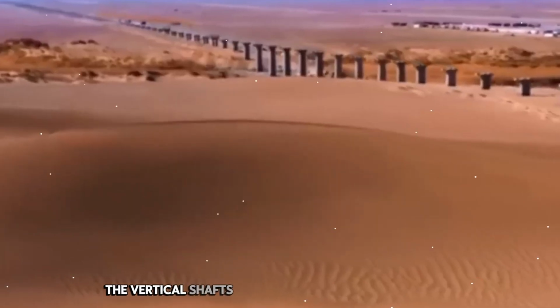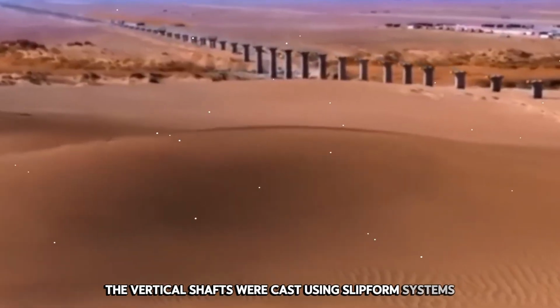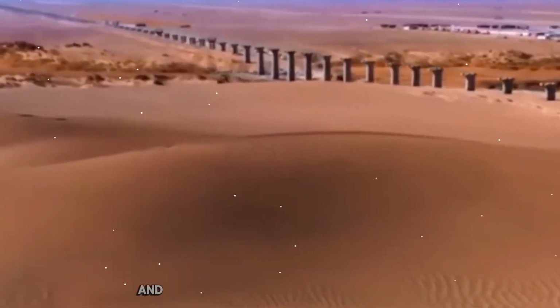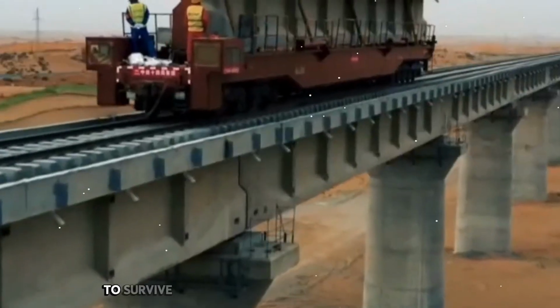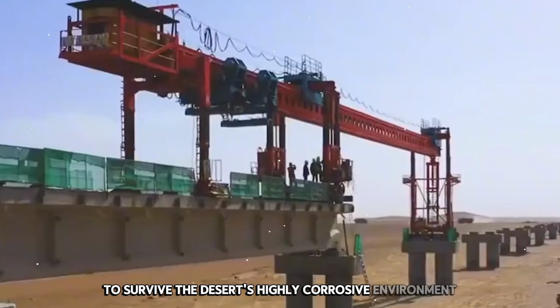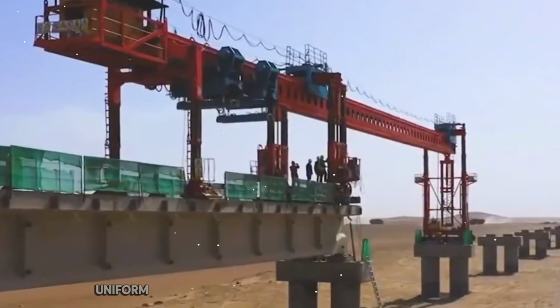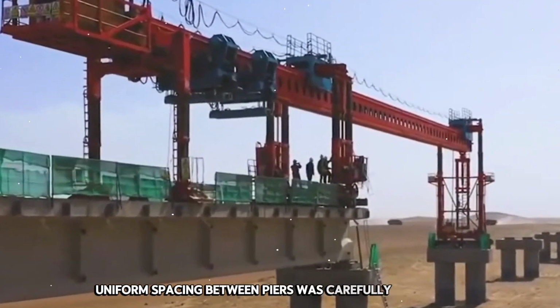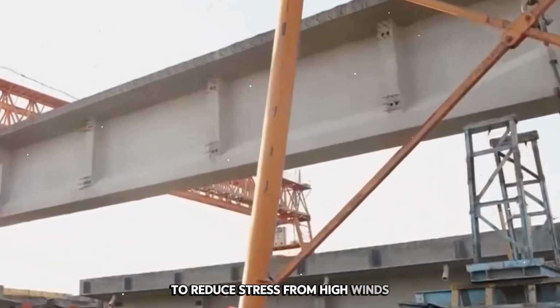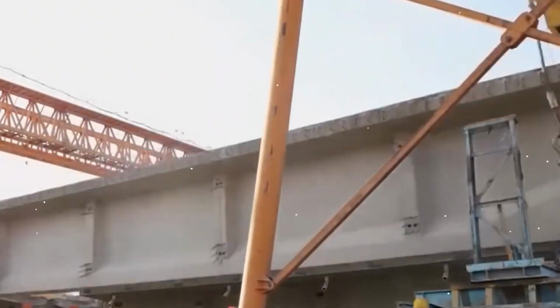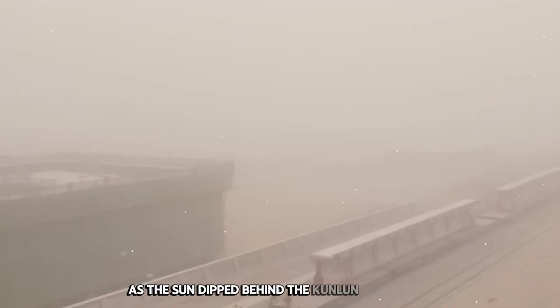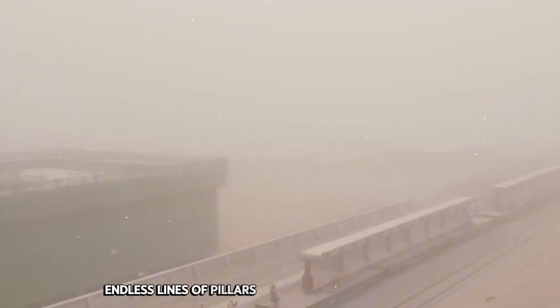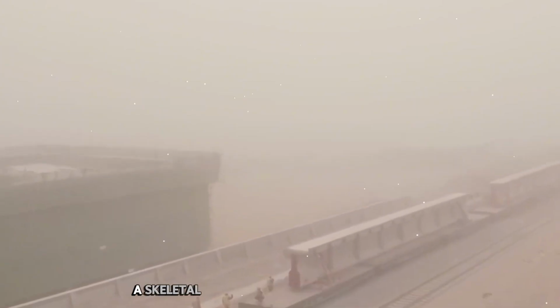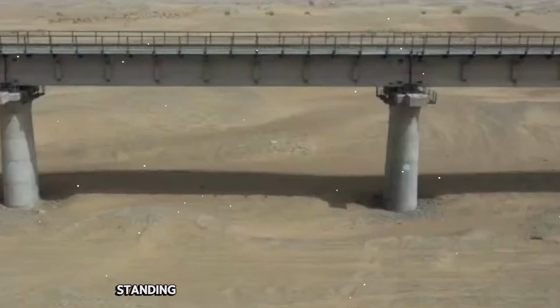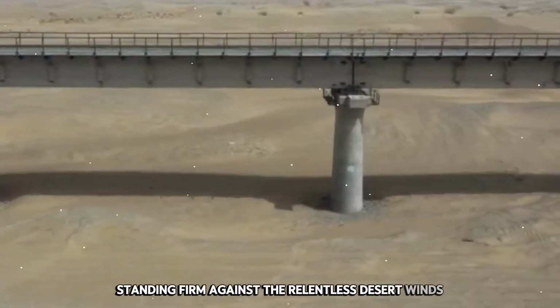The vertical shafts were cast using slip-form systems, reinforced with galvanized steel and enhanced with salt-resistant additives to survive the desert's highly corrosive environment. The short, uniform spacing between piers was carefully engineered to reduce stress from high winds and extreme temperature swings. As the sun dipped behind the Kunlun Mountains, endless lines of pillars extended toward the horizon, a skeletal framework of steel and concrete standing firm against the relentless desert winds.